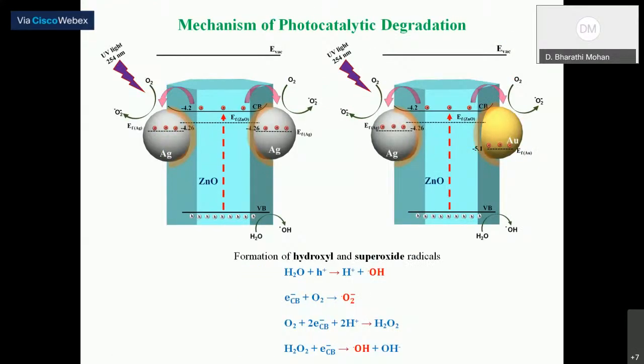What is the mechanism of the photocatalytic reaction here? We all know that zinc oxide is a very good material for the photocatalytic reaction. And once you excite with the light, electron goes from valence band to the conduction band. Electrons combine with the oxygen, or get trapped with oxygen and form superoxide, whereas holes in the valence band react with water, forming hydroxyl radicals. So the formation of hydroxyl and superoxide radicals will degrade the organic molecules into inorganic molecules. This way, the rhodamine 6G that is drop casted on the SERS platform has been degraded with the help of photocatalytic degradation technique.